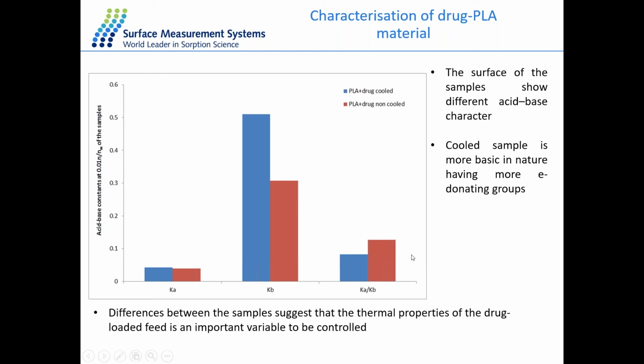What we can then also do is calculate the Ka and Kb for the surface of the samples. And what we can see is that for the cooled sample, we have a general trend of smaller Ka compared to Kb, and we can see that the cooled sample has a higher Kb. So we can say that this is more basic in nature than our non-cooled sample. So it has more electron donating groups on the surface of the sample.